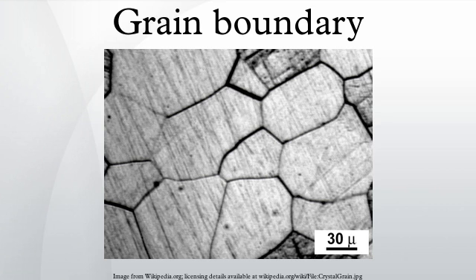An alternative is a twist boundary where the misorientation occurs around an axis that is perpendicular to the boundary plane. This type of boundary incorporates two sets of screw dislocations. If the Burgers vectors of the dislocations are orthogonal, then the dislocations do not strongly interact and form a square network. In other cases, the dislocations may interact to form a more complex hexagonal structure. These concepts of tilt and twist boundaries represent somewhat idealized cases.